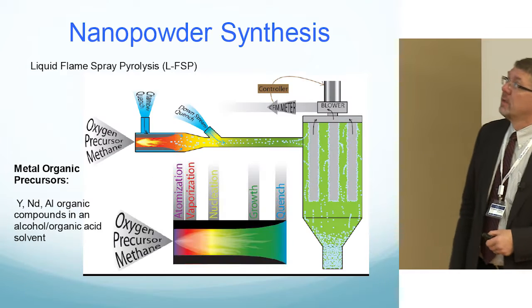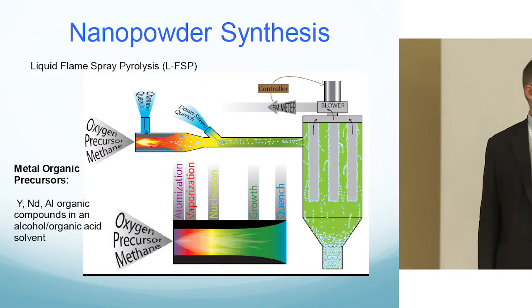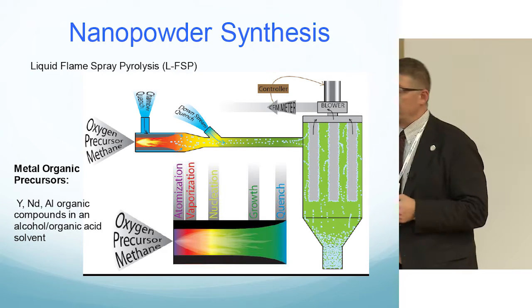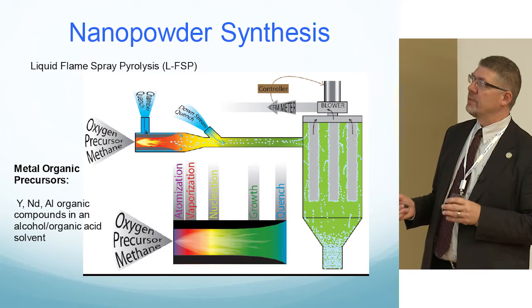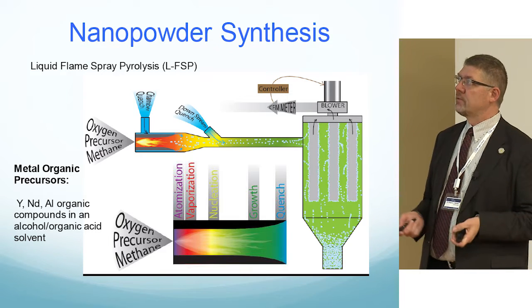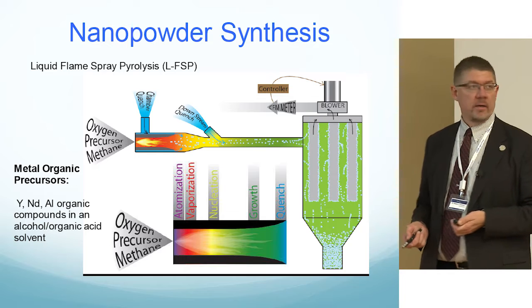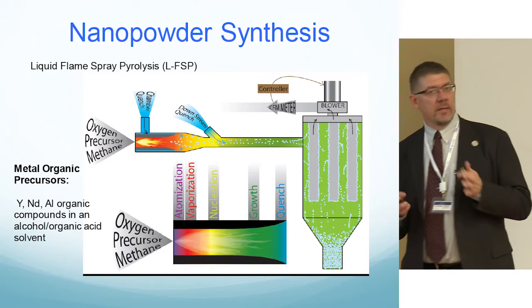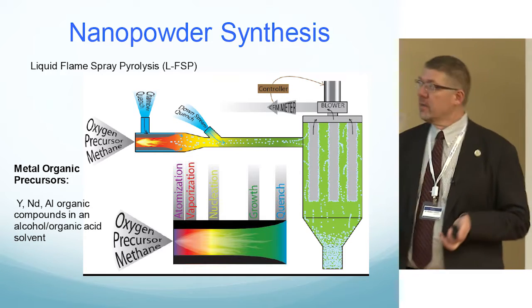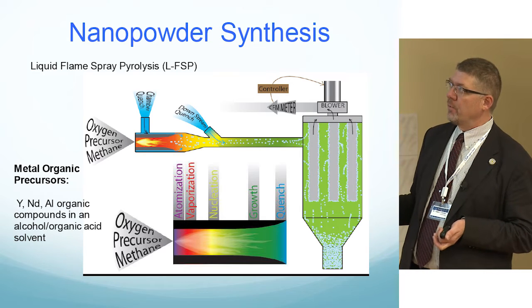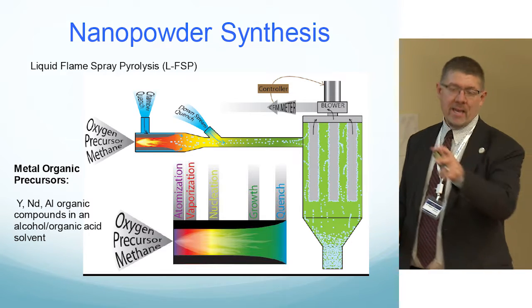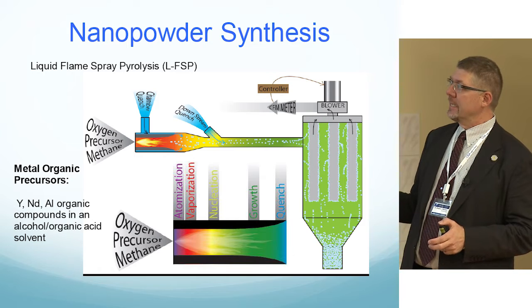Okay, we'll skip that. Another way to make the powders, besides the two you just saw here, is the way that NanoCerox makes it up in Detroit and several other groups do it. It's a flame spray pyrolysis technique. And as I tell everybody, it's capturing smoke in a bag. You start with liquids, metal organic precursors. You blow that liquid into a furnace like this one.